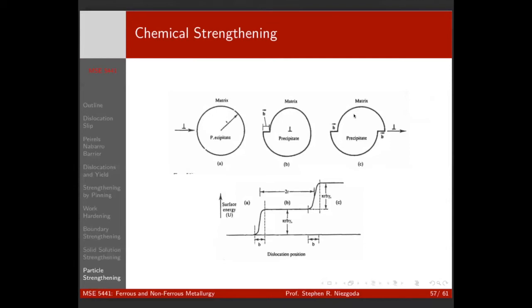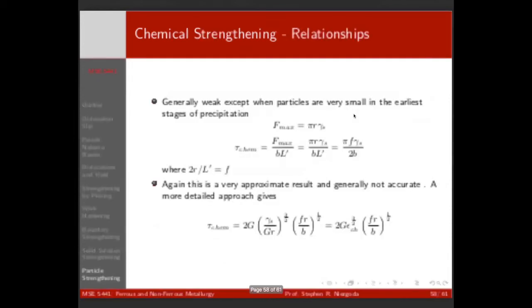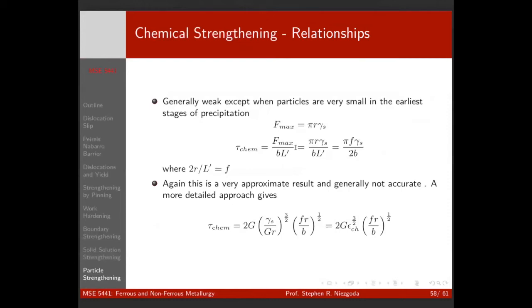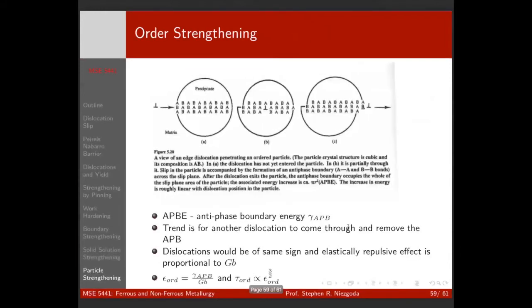Also, if you think about a dislocation source, a Frank-Read source that's pumping out dislocation after dislocation, they're all on the same plane. So generally, you'll have a particle that's cut by multiple dislocations, each one making a step, right? So in that case, you can add a pretty significant amount of surface area, right? Of course, if you do that too many times, then you've destroyed your particle, and then it becomes softer. But initially, you can create a pretty big increase in surface area, right? And again, it's the same thing. We've got a term, this is the fractional amount of new surface energy that's going to be created, right?